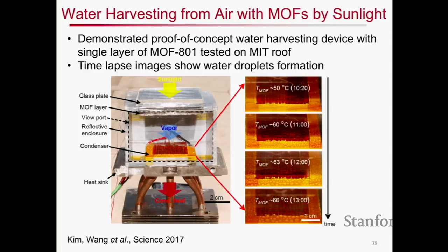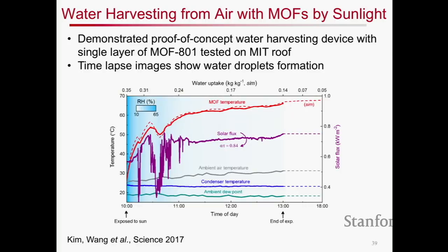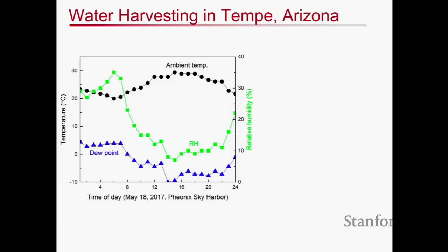In our initial design, we used still a pretty elaborate setup where, while we claimed that we can do this passively, initially we focused on having much more controlled environments. So we used a thermoelectric cooler. But what we've moved forward towards is not only just demonstrating this design, but thinking about whether we can do this more practically and also demonstrate it in a climate where the relative humidity is low.